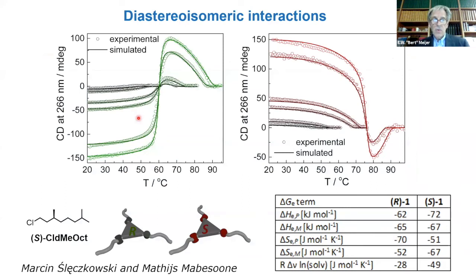It is a complicated slide, but I will bring you through. What we've done here, we took a chiral solvent and we compared the chiral solvent in one enantiomer versus the chiral solvent in the other enantiomer. And then we looked at the data as a function of concentration with the real experimental data, and we simulated it with a model that I'm not going to explain. At first instance, they look like mirror images. But if you carefully look at it, then you see for the R, the temperature at which it goes from one helical form to the other is at 60 degrees, while here it is at 75 degrees. And if you then take all of the data together, you will see that on the enthalpy and entropy, there's hardly any diastereomeric relationship. The real reason comes from the role of the solvent.